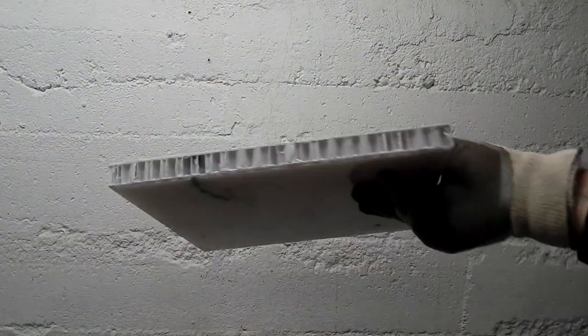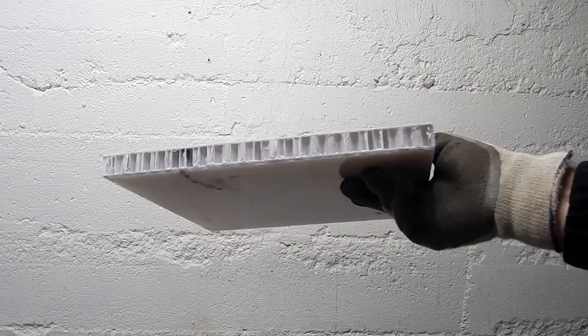It's an interesting look at a way to build a cored panel open molded using this relatively light polypropylene core, which is tough, stiff, and a lot lighter than balsa. And in some ways easier to deal with than foam because of the air just runs through the semi-permeable scrim on the surface.